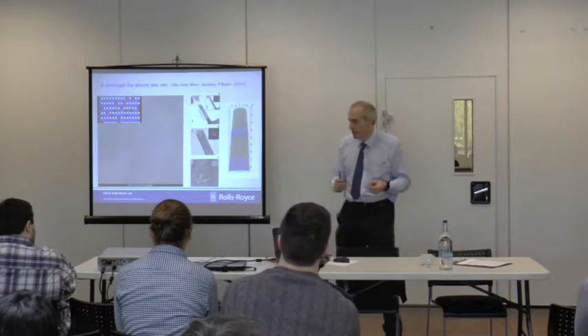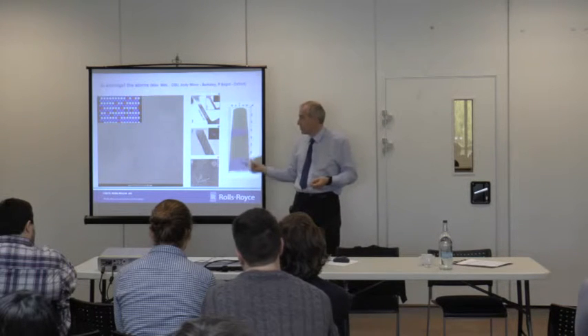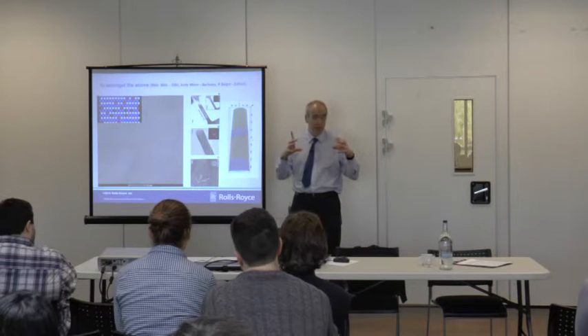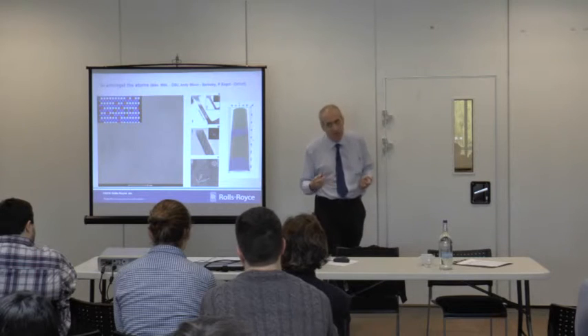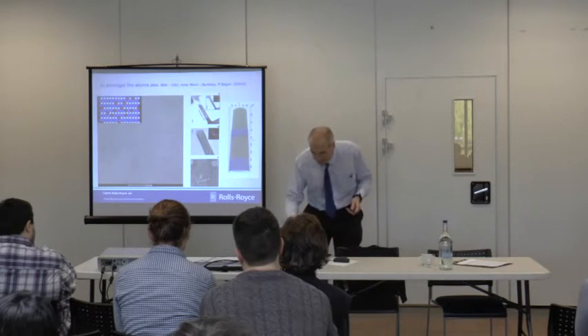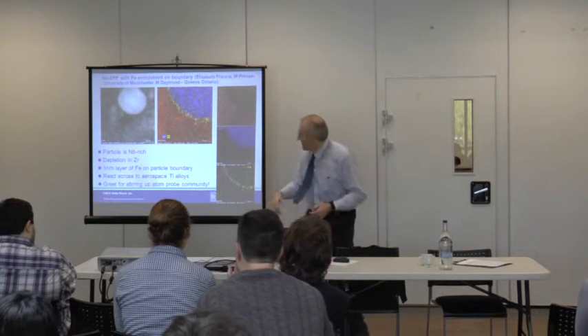So essentially it's a spatially resolved mass spectrometer, and you get about half the atoms. So we've had stuff out of engines where we've literally torn it apart atom from atom and then built up the full 3D atomic map of what's in there. And that allows us to understand the chemistry of interfaces and the chemistry of very, very small precipitates, which can be critical in dictating behaviour. I really need to accelerate some more.